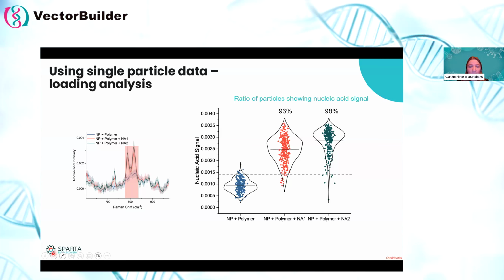So what I can do is set a threshold on the unloaded control, a statistical threshold, and then we can compare the percentage of loaded particles. So you see that for both of these conditions, it's very high. It's at 96 and 98%. And just to note, you'll see there's quite a spread in this data.